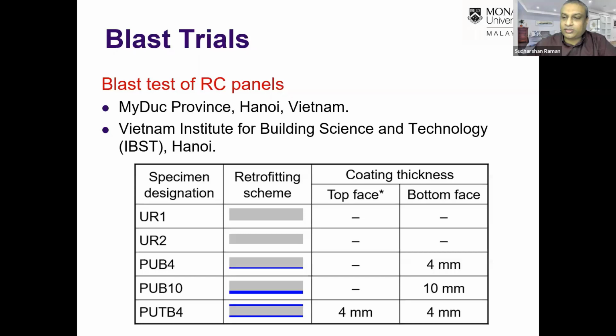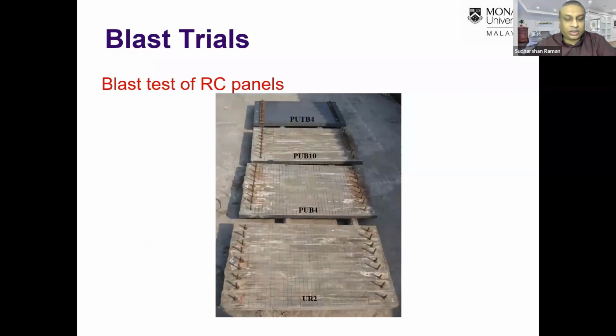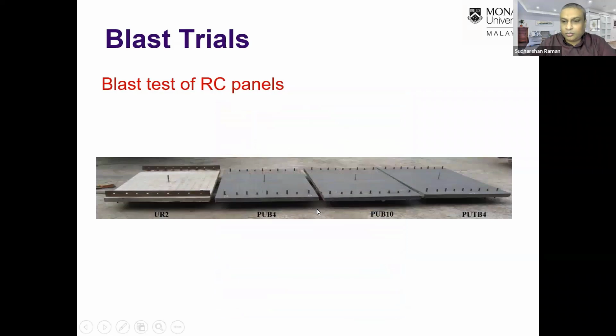PUB4 is polyurea applied on the bottom surface at 4 millimeters. PUB10 is on the bottom surface at 10 millimeters. PUTB4 is top and bottom surface, 4 millimeters on each face. So these were the panels prepared for the blast trials in Vietnam. And this is the top surface. Only PUTB4 was coated on the top surface, as you can see here. And then this is the bottom surface.